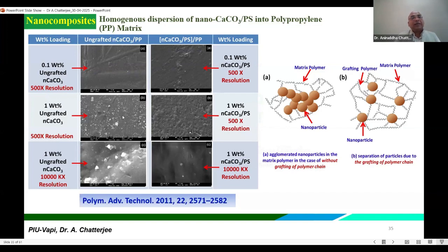But when we increase the percentage from 0.1 to 1, you can observe a clear difference. For ungrafted calcium carbonate, the particles are on the surface, but with grafted nanoparticles, maximum particles are integrated with the polymeric matrix, meaning they are inside the matrix. They are uniformly dispersed. And this is the high resolution picture. Here you can see the aggregation of nanoparticles with the same 1% loading for ungrafted calcium carbonate nanoparticles. But here all nanoparticles are uniformly dispersed in the polymeric matrix.